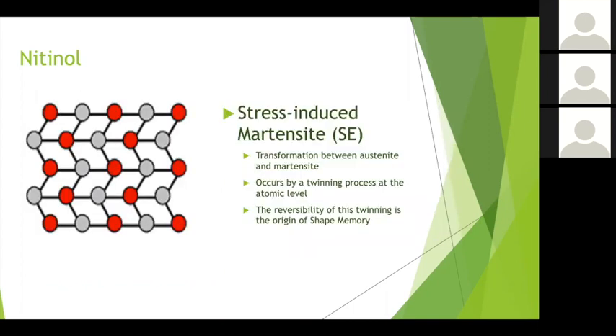But if we were to take austenite just by itself in a straight rigid phase, we can't really use it in nickel titanium, or we can't use it in rotary instrumentation. Nitinol is unique because we have both properties of austenite and martensite inside of the metal itself. So the reason that an austenite file, such as a twisted file, can bend and follow curvature of canals is due to what we call stress-induced martensite.